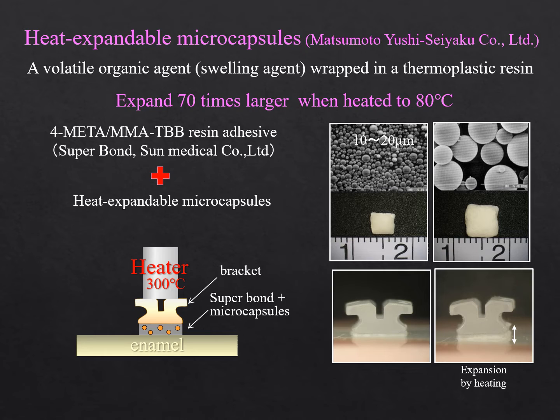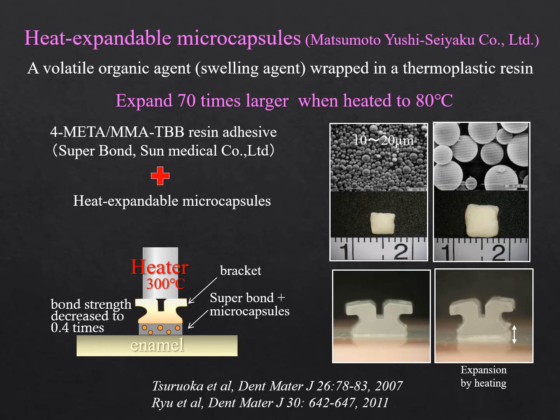We reported that when the bracket bonded with this prototype adhesive was heated with a 300-degree heater, the bond strength decreased to 0.4 times that before heating, using metal brackets. We also reported similar results using the ceramic brackets, as shown in the papers. However, considering the clinical application, it is necessary to find a safer heating method, because a 300-degree heater may cause burns of surrounding soft tissues.